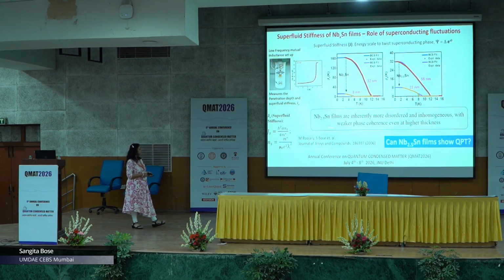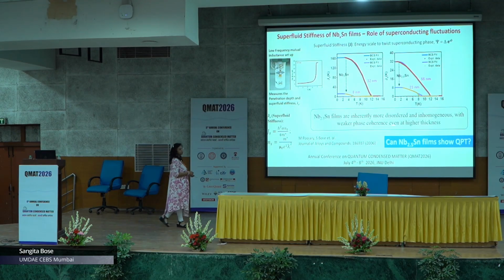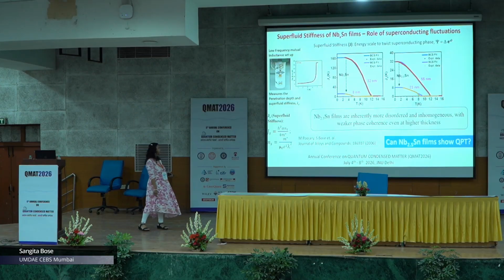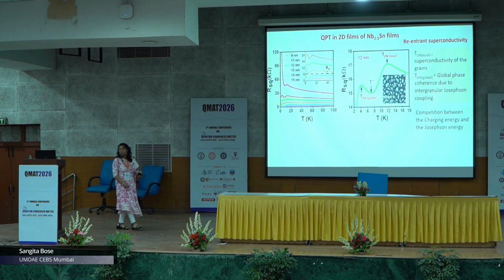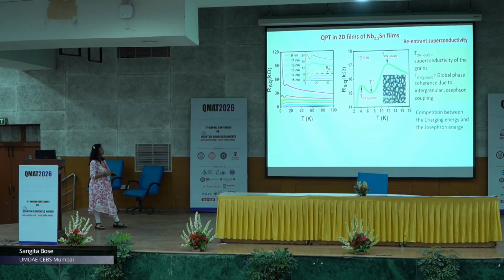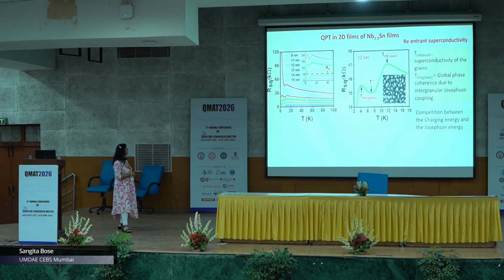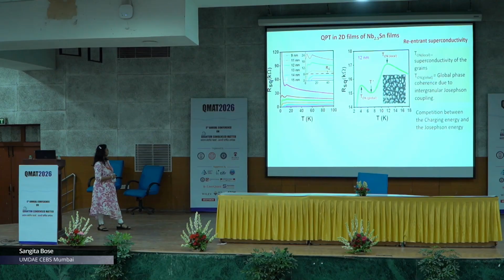So we conclude that these niobium 2.5 tin films are inherently more disordered and inhomogeneous, with weaker phase coherence even at extremely high thickness. And therefore, we pose the question whether these films can show some kind of a quantum phase transition. So now I will concentrate only on these niobium 2.5 tin films. As I already showed in this data, as you decrease the film thickness, you go from this superconductor to these insulating films. What is interesting to note is that this does not happen in one shot, but you see some kind of a reentrant behavior.